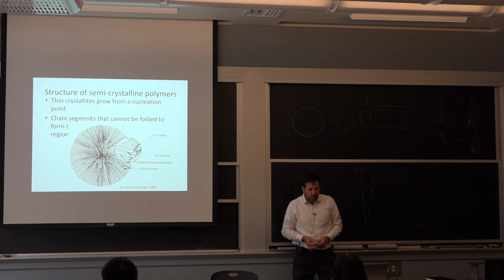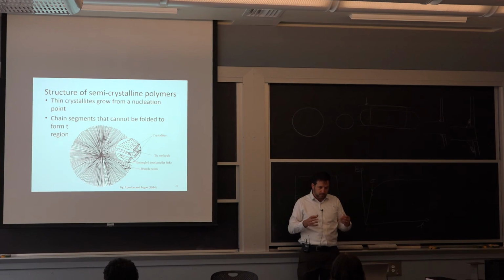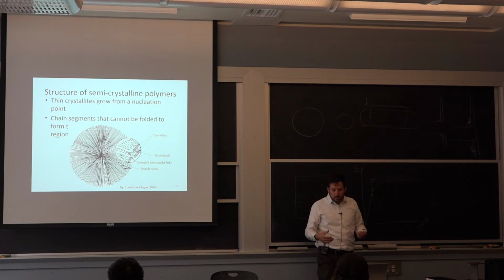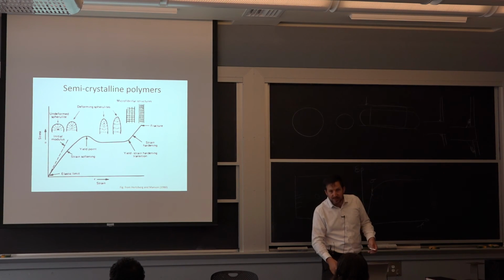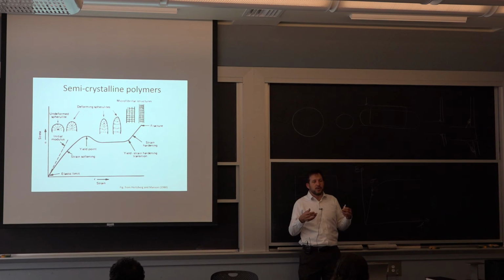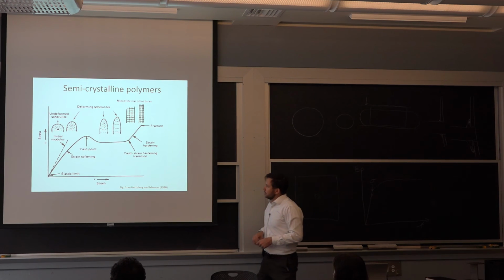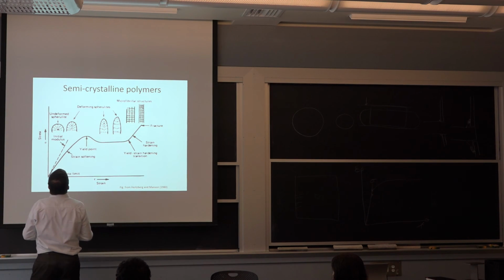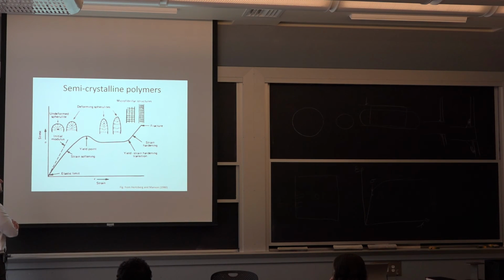Just to add a little bit to our story here for the deformation, we're dealing with a multi-component system. So there's some amorphous zone and there's the crystal zones. A lot of times most of the stretch that we get from creep is in the amorphous zone. So one reason we can use polyethylene is because it has crystals in it. If it wasn't for the crystallinity in polyethylene, it'd be so soft that you couldn't use it as a structural material.